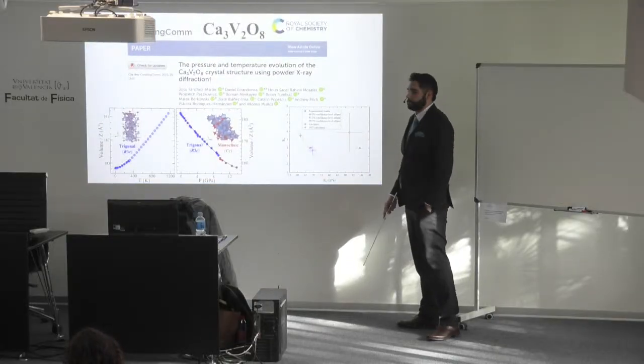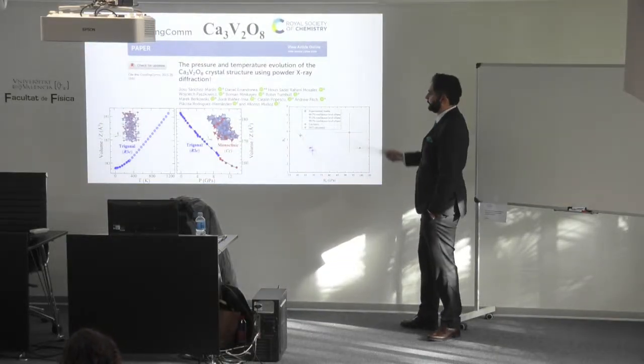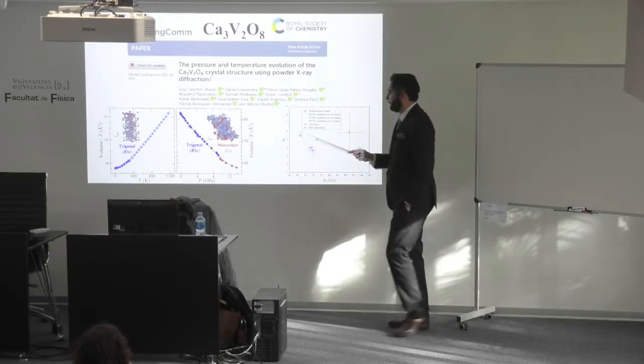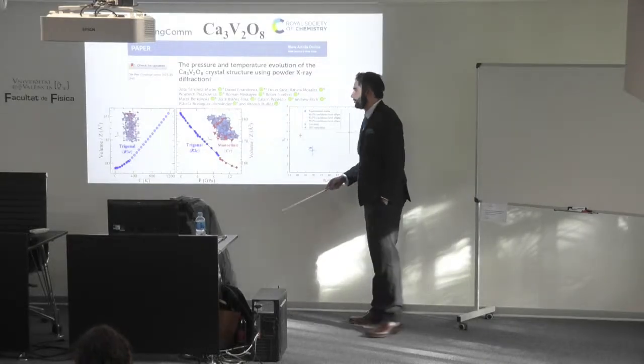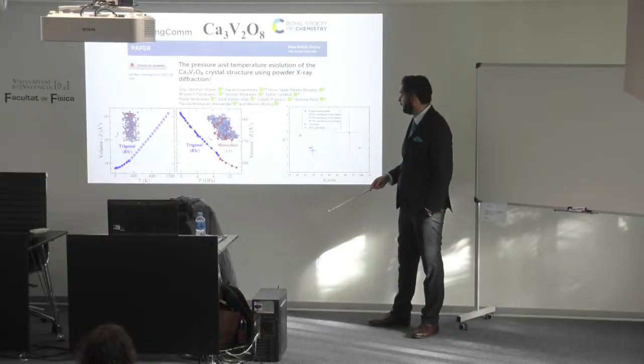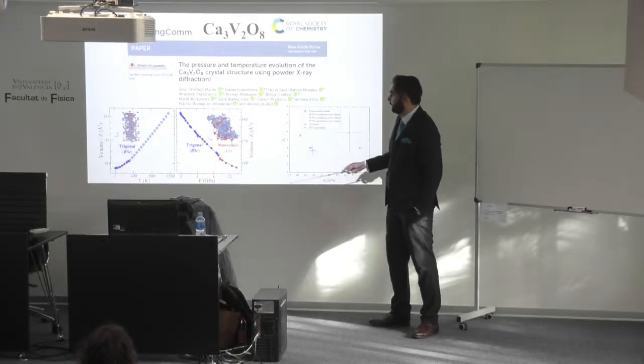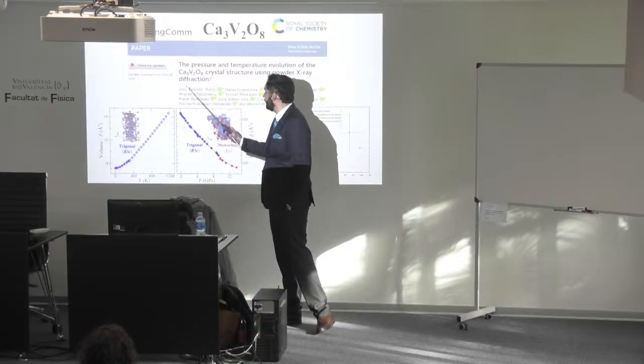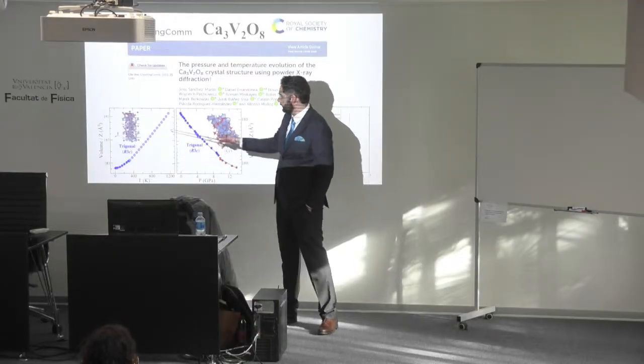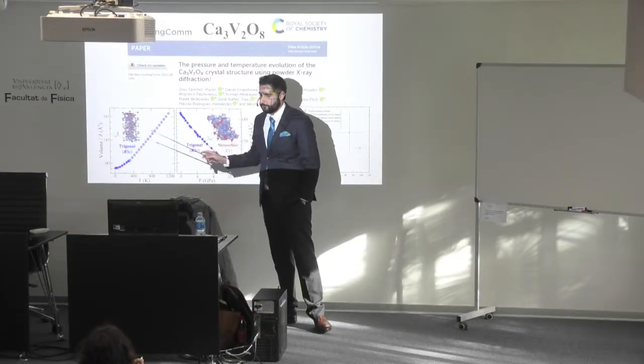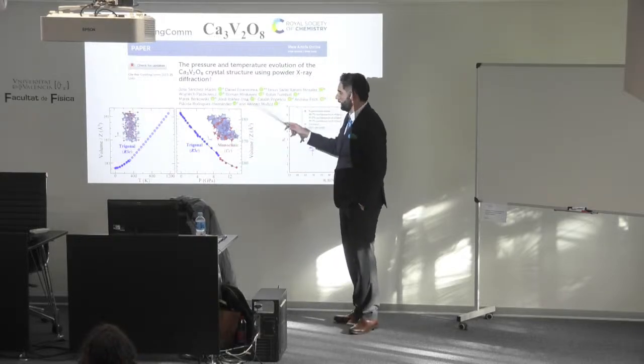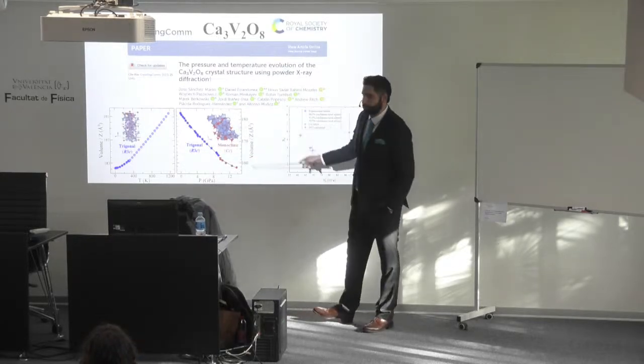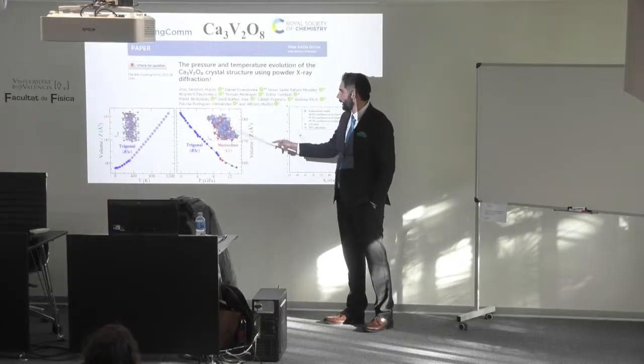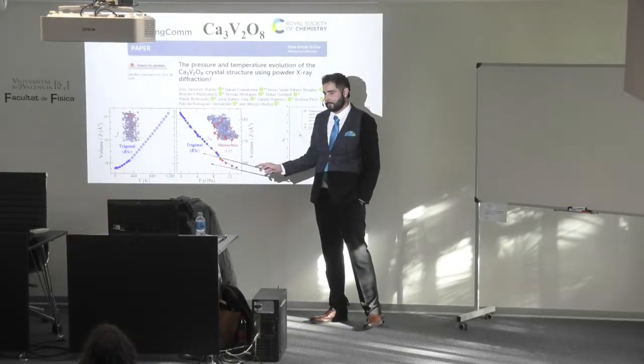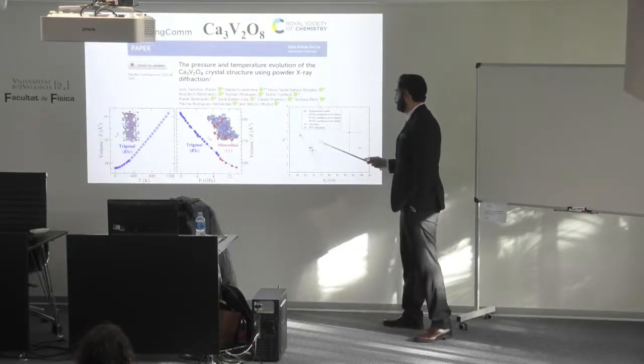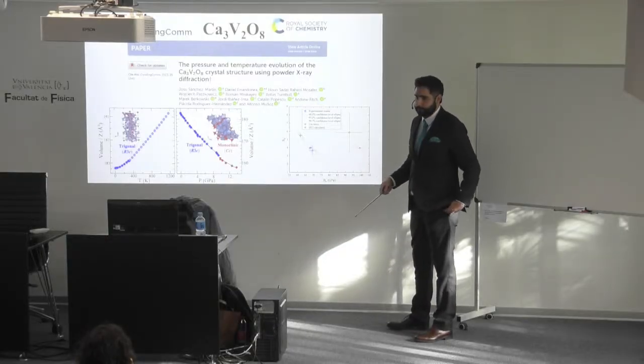So for calcium orthovanadate, this is a divalent metal, so it's a different family. We have a collaboration with Professor Paszkowicz in Warsaw, and this one has a special structure, this whitlockite-type trigonal structure that is huge, and they did the temperature measurements, we did pressure measurements, and got to see a phase transition that is not seen with temperature. These were new. And we also got to update the pressure data that we had previously.